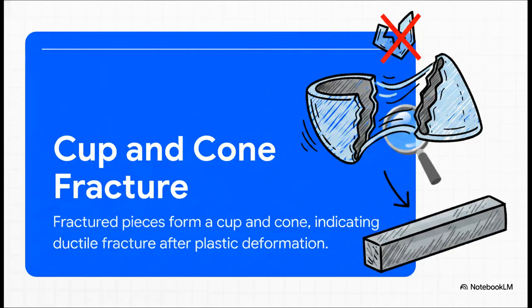When structural steel does finally fracture, engineers are hoping to see a very specific signature, a cup and cone fracture. This is where one broken end forms a cup shape and the other forms a cone that fits perfectly inside it. Why is this so vital? Well, a cup and cone pattern proves that the steel suffered a ductile fracture. It means the steel deformed and stretched significantly before failing, giving us plenty of warning, rather than just shattering abruptly without warning, like a pane of glass.